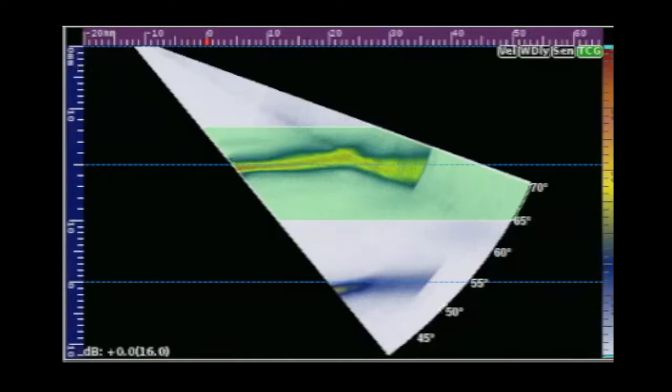That's why the echodynamic does this little jog at 60 degrees — the loudest part isn't lined up with the corner trap. And this is why we care: when you're doing weld inspection and you find a surface-connected flaw like a crack, lack of fusion, or lack of penetration, you may find that the indication doesn't actually peak at the surface. There's not much you can do to calibrate this out at around 60 degrees — that signal is going to drift either into the first leg or into the second leg. With phased array scanning at a fixed offset, you may just choose to design the scan plan so that you don't hit the root at 60 degrees and kind of avoid this problem altogether.